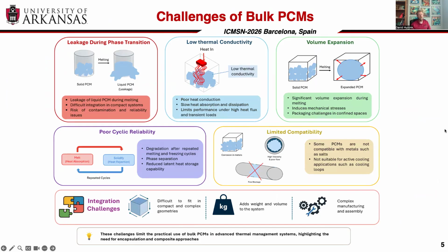But also with the phase change materials of interest in electronic systems for the melting temperatures that we're interested in, it limits us pretty much to organic phase change materials, which tend to have very low thermal conductivity, which again is a drawback in the thermal management system. You want to have something to have fast or expedient heat removal through a high conductivity system.